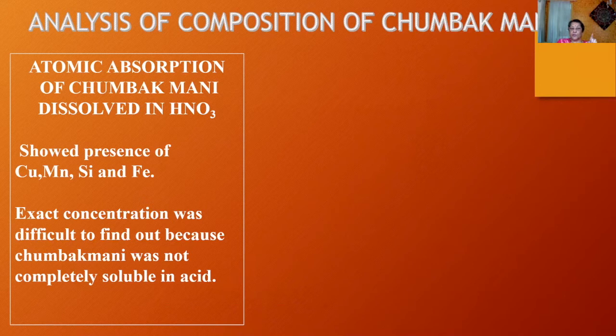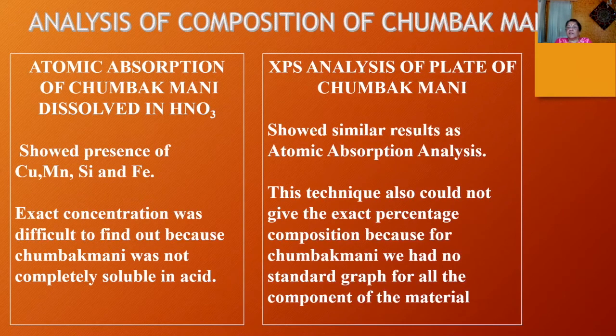But it showed the presence of copper, manganese, silicon, and iron. These metals were present in Chumbak Mani, which was shiny. But atomic absorption could not tell us the concentration or the percentage, because Chumbak Mani didn't completely dissolve in it. Some part of it didn't dissolve and remained at the bottom. Then we did XPS analysis, but this time we did the analysis of the plate.